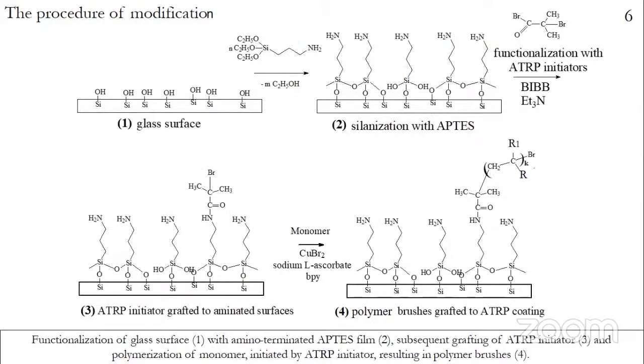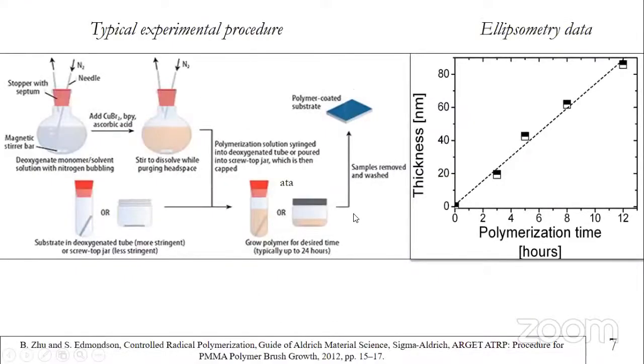Okay, in this slide, you can see a scheme of this methodology. The grafted polymer brushes attached to glass are fabricated in a three-step process. On the first stage, we fabricate the amino-functionalized substrate. On the second stage, initiator grafting. And the third stage, polymerization of our brushes. The third stage is shown on the slide.